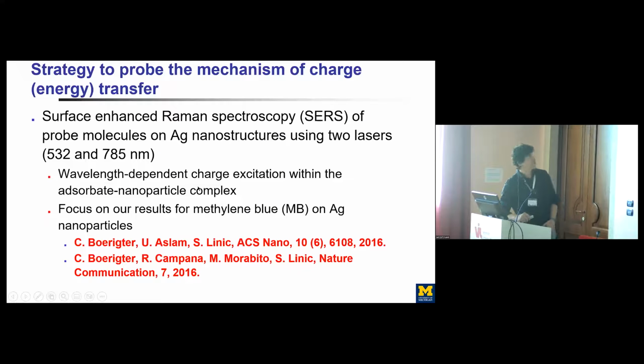So to answer this question, we used a model system where we basically covered the surface of these nanoparticles with dye molecules. And we used surface enhanced Raman spectroscopy using different lasers, different wavelengths, to monitor whether we can observe the signatures of the charge excitation at that interface or at the molecule. And I'm going to explain our results today by just focusing on methylene blue, but we have done a large number of these organic dyes deposited on the silver surface.